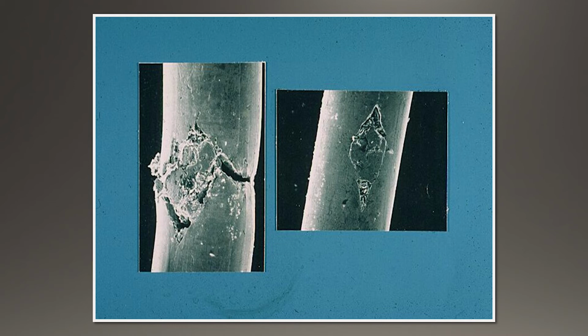Sometimes the inclusion actually falls out when it breaks and is not present. If it is present, there's only a 50-50 chance it'll be left in the end of the wire that's left in the wire drawing machine. So because of the absence of inclusions, probably 85% of the time, if it's an inclusion-related break, you don't know what the origin was, and you can't tell what the actual mechanism was at the beginning.